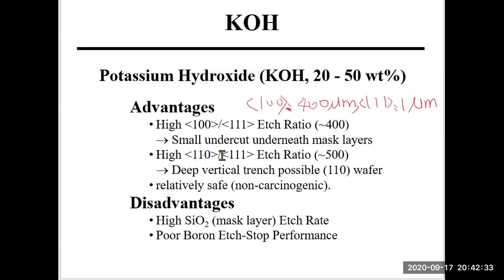And the 110 over 111 etch ratio is even higher, about 500. So this leads to deep vertical trenches on a 110 wafer. KOH is also relatively safe and non-carcinogenic, so it's much more widely used than EDP. Disadvantage: high silicon dioxide etch rate. So if you use silicon dioxide as a mask layer for KOH, this layer needs to be thick enough.